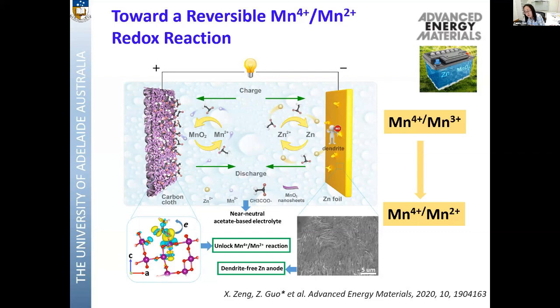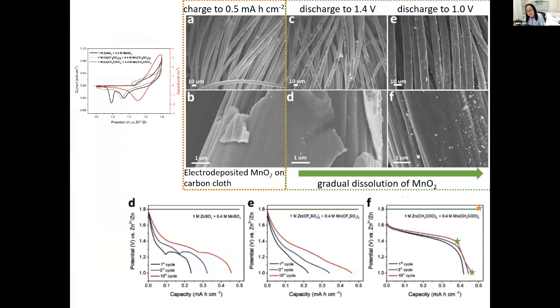So in this case, we don't need to worry about the manganese dissolution, the phase change, and the structure degrading. You can see this is in situ SEM data. When we charge to a certain capacity, this manganese oxide deposits on the surface of the substrate on the cathode side. When we discharge to a certain voltage, this manganese oxide starts to dissolve. When we deep discharge to 1.0 volt, almost all the manganese oxide is dissolved. So this verifies the reaction is actually a deposition dissolution reaction.